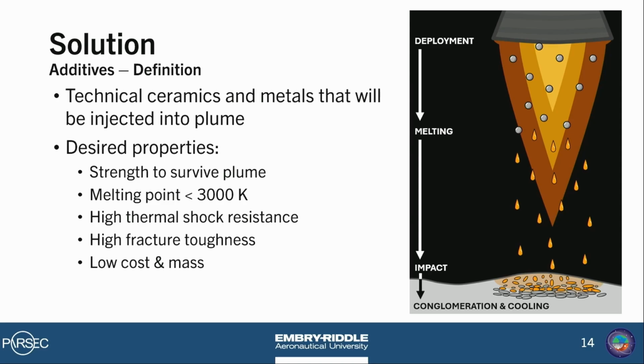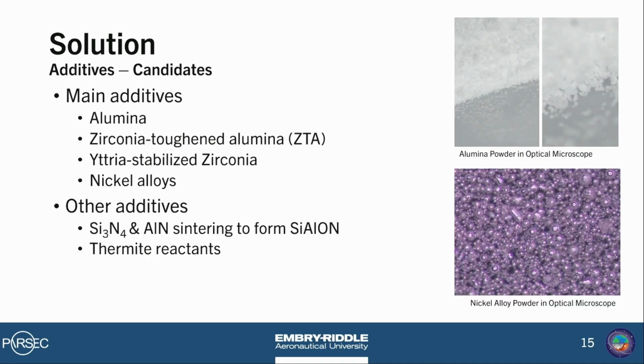we've compiled a list of candidate additives with a set of desirable properties, including a strength high enough for our landing pad to survive the forces from the plume, a melting point less than 3,000 Kelvin, which is around the temperature that we expect the plume to be, a relatively high thermal shock resistance so that the landing pad can survive rapid changes in temperature, a high fracture toughness to ensure that flaws in the landing pad are less likely to grow into fractures, and of course, low cost and mass.